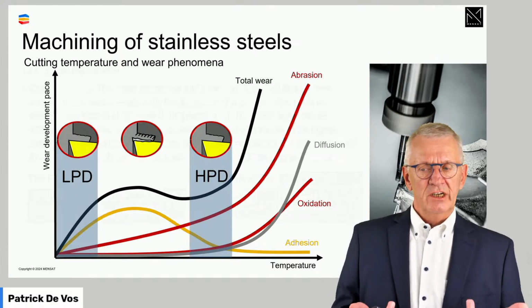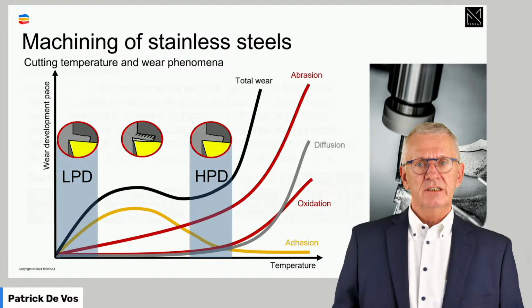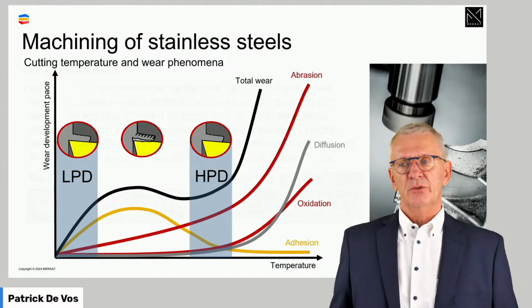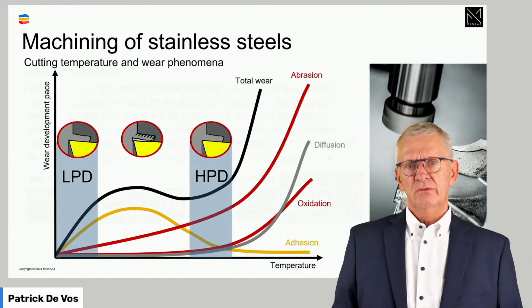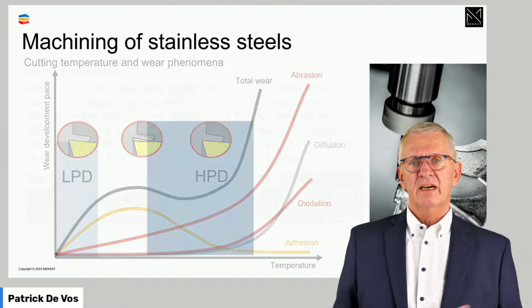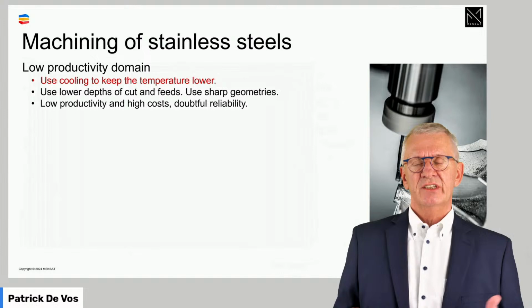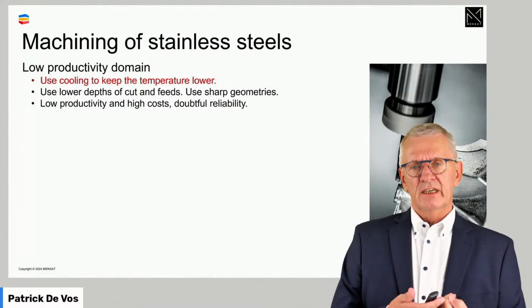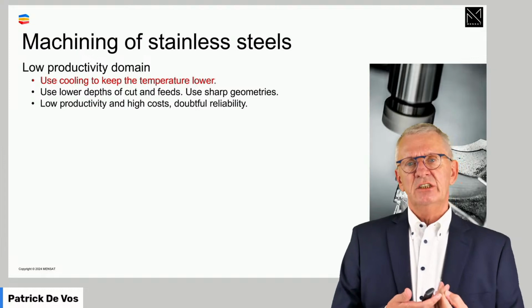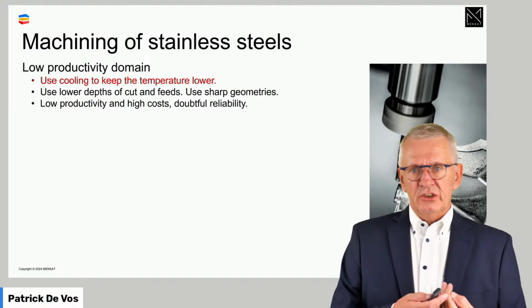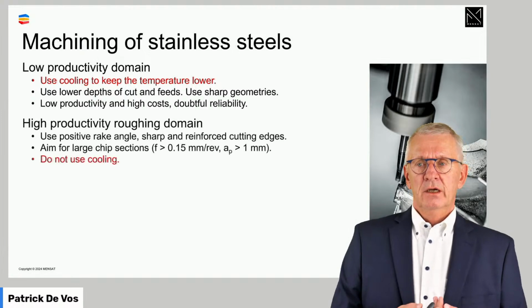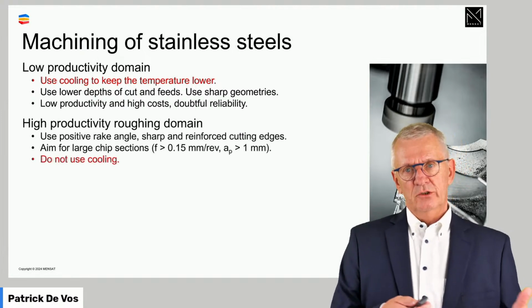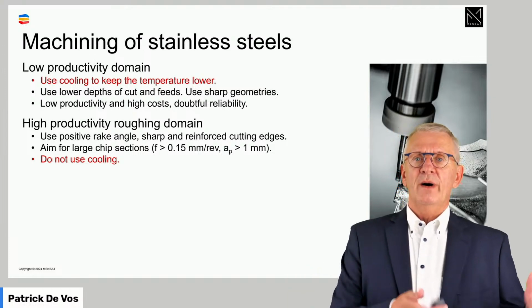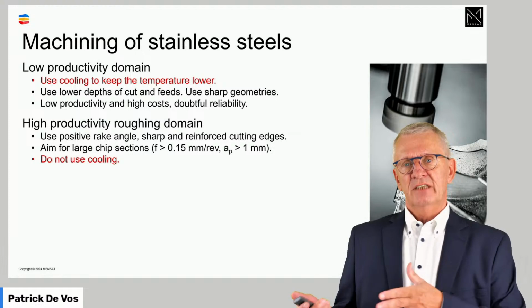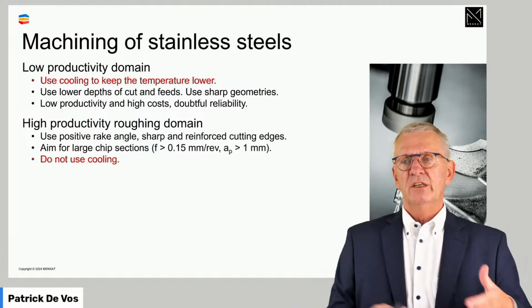Adhesive wear and galling wear, the picture is different. That will happen at certain critical temperatures. And if your temperature is lower or higher, then it will disappear again. That means that in stainless steels, we talk about a low productivity domain and a high productivity domain. Low means that you keep your temperature lower than a certain critical value to make sure that adhesive wear does not take too much out of the cutting. High productivity means that you are able to take your cutting speed high enough to pass the dangerous zone, and again have temperatures which are not favorable for build-up edges to be formed.